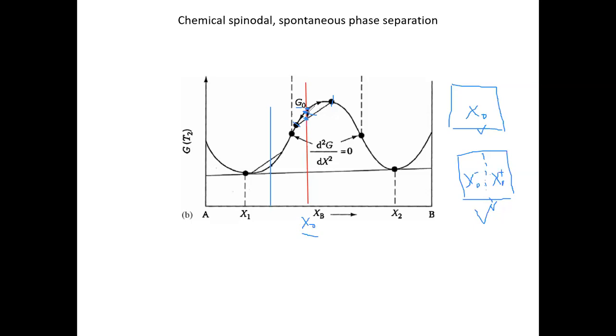Now, how about if we further increase the contrast? Suppose that I flow more atoms to the right region and take more atoms from the left region, so I increase the contrast between X naught minus and X naught plus. What are we going to see in those cases? Well, as these compositions further separate and move far away from one another, your overall free energy keeps on decreasing, right? As the system keeps on developing this separation of composition, you reach the minimum free energy once your system reaches the equilibrium composition predicted by the phase diagram, which is the lowest free energy that you can ever achieve, right?